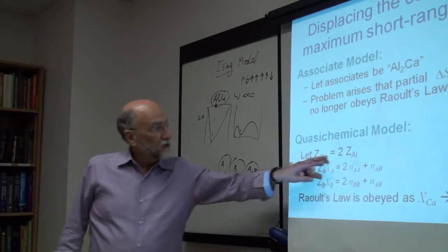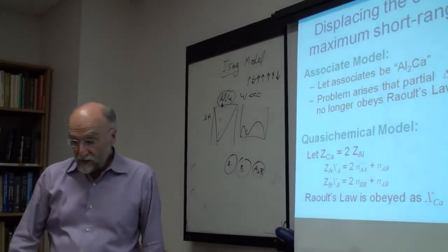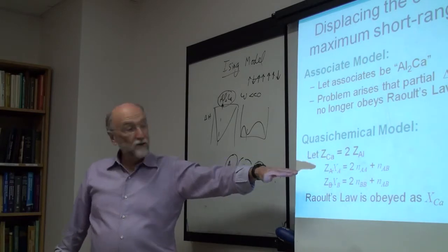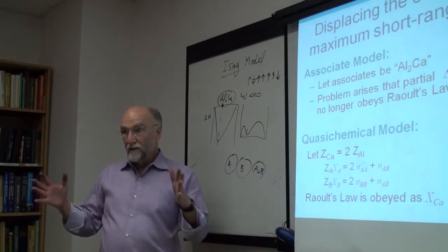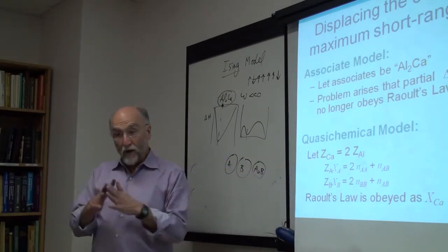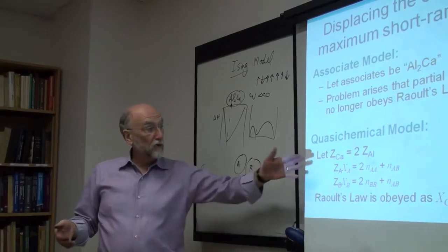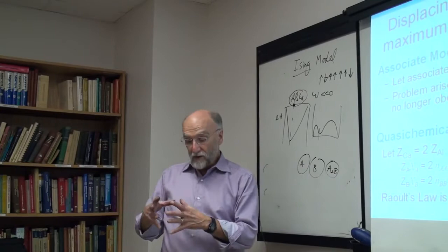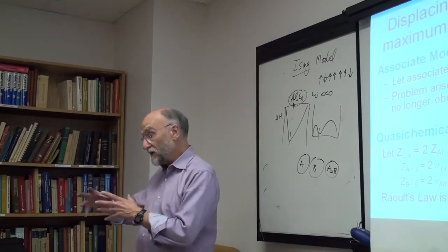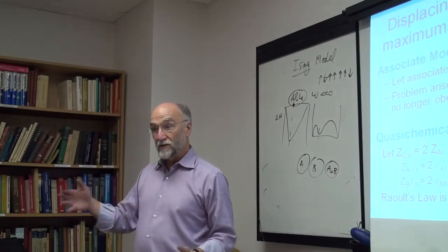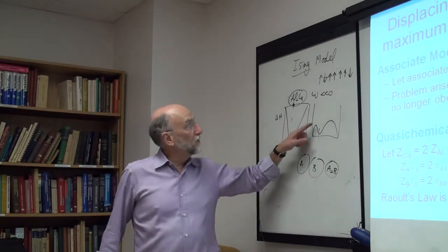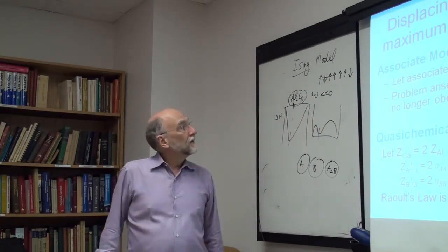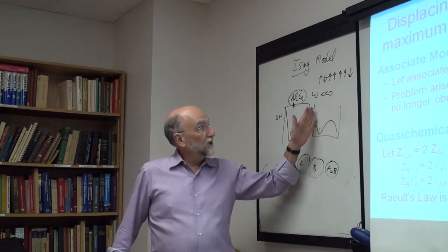Now this you cannot do in a solid solution. In a solid solution you have one phase, a single structure, so the coordination number can't be changing. But this is possible in a liquid. In a liquid, the coordination number can vary as you move across the system. So calcium and aluminum can be completely miscible in the liquid state, and the coordination number changes as you move.